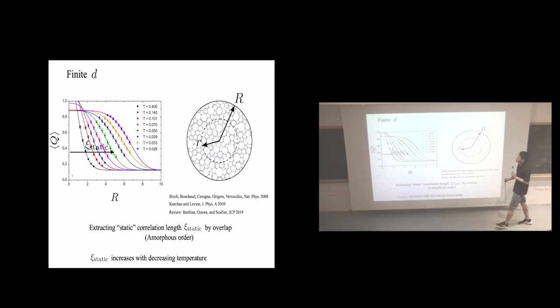So in the case of finite dimension, in 2D and 3D, we have a spatial structure. Okay. So in that case, we can measure a sort of static correlation length scale using the overlap function. I'm not going into detail, but as I mentioned, if you look at the static structure, it's hard to detect some sort of order by just looking at it, but by using some overlap analysis, we can look at the spatial profile of the overlap function. And at high temperature, it decays quickly, but with decreasing temperature, it decays very slowly along the radial direction. And we can extract static correlation lengths. But again, by just looking at the structure, it's hard to see some sort of order. Therefore, people call it amorphous order.